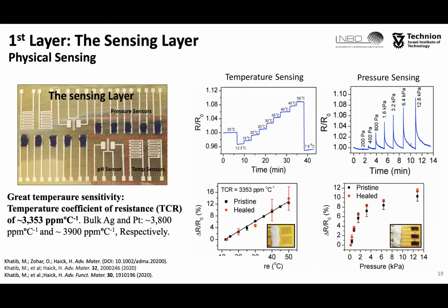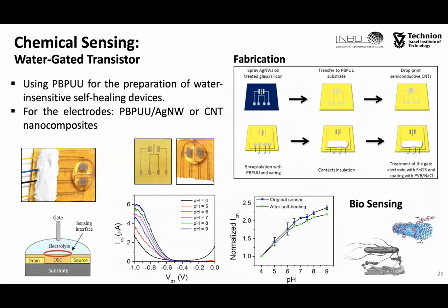We have shown that the composite is very sensitive to pressure as low as 200 Pascal and has shown high recovery before and after mechanical damages. Three minutes. Okay.